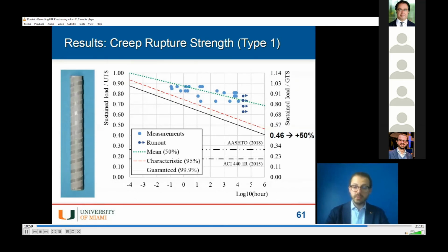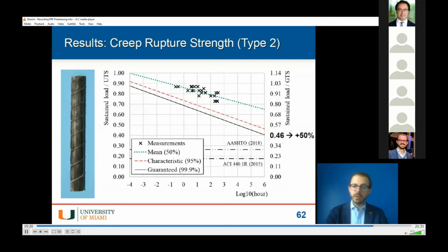By applying an additional safety factor, we get to the value of 0.46. That is more than 50%, the limit that is currently imposed by ACI, and would allow for a much more efficient and effective design against rupture of reinforced concrete structures and prestressed concrete structures. We get the same results on the type 2 bar, even though we're dealing with a different kind of surface preparation. This is interesting because it may imply, and needs to be confirmed on a larger data set, that the type of surface preparation we have in our bar does not really affect its rupture behavior.